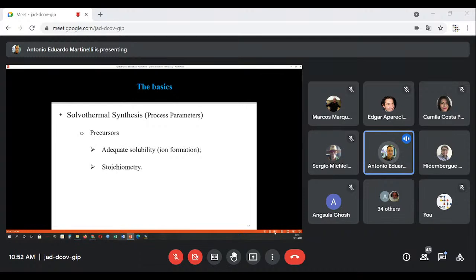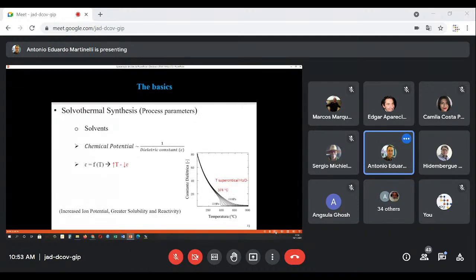Let's talk about some process parameters, starting with the precursors. The precursors should allow adequate solubility for the release of ions that will be used in the formation of the target material, and also used in the stoichiometric way. As for the solvents, the chemical potential of ions dispersed in a solvent is inversely proportional to the dielectric constant of that medium. This relationship affects the solubility of precursors or intermediate compounds formed in the synthesis.